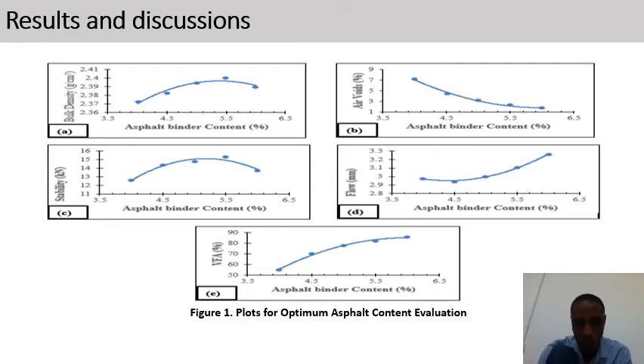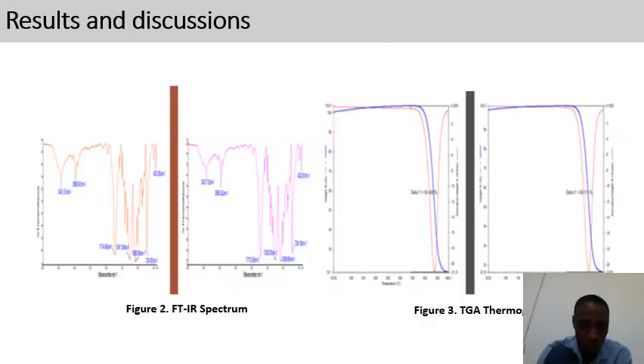All these were selected based on JKR standard specification for roads. Also, after exposing this PET to gamma irradiation, there is need to check the effect of irradiation on the properties of this PET. So FTIR and TGA were carried out to ascertain the effect of this irradiation on the PET.